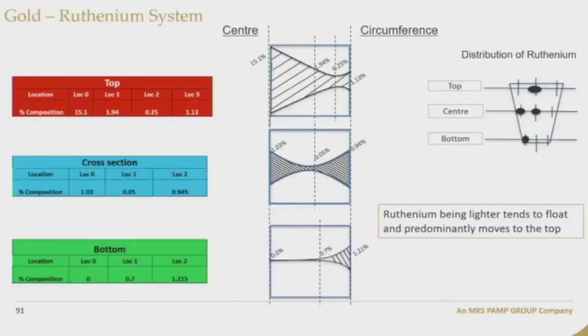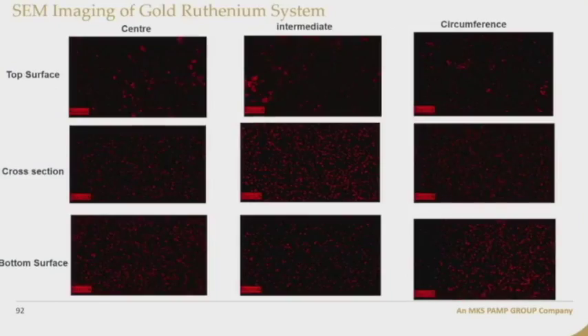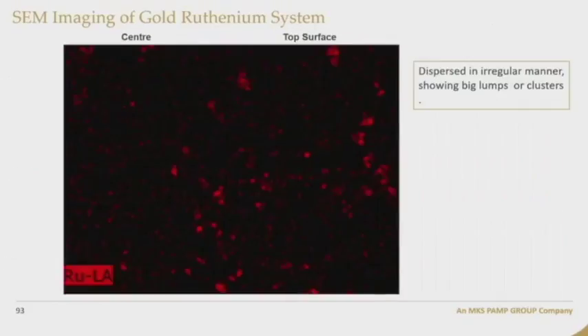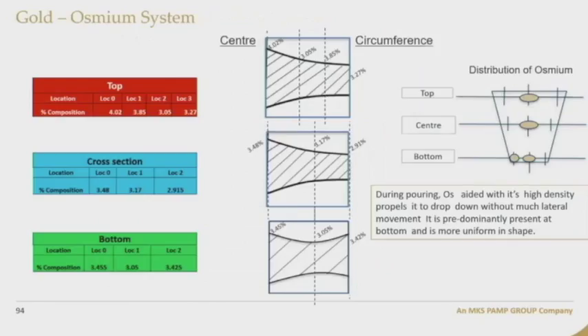Same thing with ruthenium, it also forms the same trend as we found in XRF, where it was found more at the top surface, also at the center, and at the bottom it was more at the periphery. So ruthenium being lighter tends to float and predominantly moves towards the top. And if you see the structure, these were at various locations, but I've expanded one, and you see it is less dense, and ruthenium atoms tend to form clusters. So it is dispersed in an irregular manner, showing big lumps and clusters.